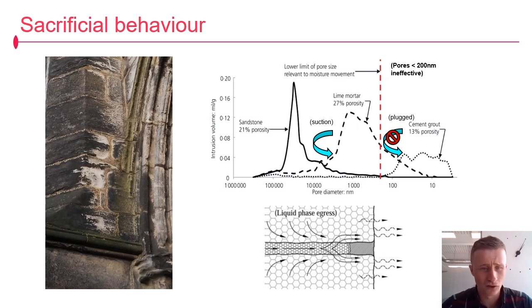With the moving water go the soluble salts, but that's plugged with a very, very nasty cement mortar. Now, you'd think, okay, the cement is again smaller in pore size than the lime. Why doesn't it just pull the water into the cement? Well, the capillary flow only occurs down to a certain pore size. By the time you get beneath 200 nanometres in pore size, capillary flow grinds to a halt, and that porosity is completely ineffective for water transport purposes. So rather than being a poultice, it's just a plug holding the water in the joint.